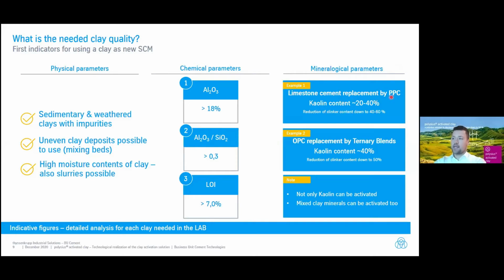But typically we are saying a kaolin content between 20 and 40% should be sufficient, depending on the case for sure. If you would like to substitute an OPC with the so-called LC3-50 cement, then a kaolin content of around 40% would be needed. If you would like to produce some lower quality cements at the end, then you can also go with some lower kaolin contents.